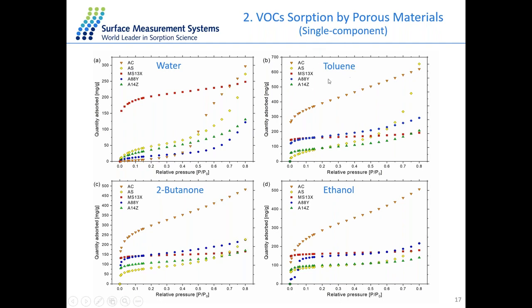Then for the toluene data here, as toluene is a more nonpolar probe molecule, it shows a very different tendency from the water molecule. This time, the triangle here is the activated charcoal, the AC sample. It shows a much higher uptake compared to the others at 80% partial pressure of toluene, with around 60% in total uptake. That means this sample has very good affinity with toluene. The previously good one, the 13X, showed very bad performance with toluene, even 5 times lower than the charcoal sample.